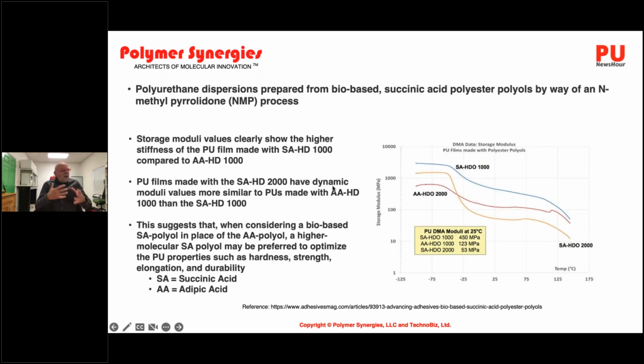These polyurethane films were made with succinic acid 2000. They have a dynamic modulus that's very similar to the polyurethanes made with adipic acid at 1000 than the succinic acid at 1000. So again, here what you're looking at is molecular weight differences resulting in differences in performance. So again, this is a structure-property-performance relationship, and here's an example of it.